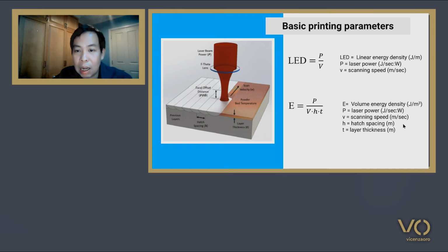So all of these, it's the energy consideration here. We calculate the volume energy density, E, in joules per cubic meter. It's calculated easily as the power divided by the scanning speed, the hatch spacing, and the layer thickness. Actually, this is how you create the volume during the scan.